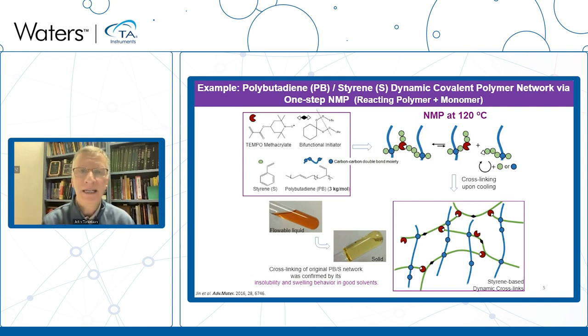And so nitroxide-mediated polymerization has been around for about 30 years, actually originated at Xerox, and this is work that we published several years ago, really bringing it into the realm of dynamic chemistry for polymer networks. And the idea is we can end up taking these materials. You can see in the burnt orange test tube where it says flowable liquid, this is prior to doing reaction. And after we do reaction, you see that we have a solid that's produced in that particular network. If we heat that solid up to 120 degrees C or higher, there is actually a dissociation of nitroxide-carbon bonds, and we can reprocess the material, and upon cooling, we actually recover the cross-link density.